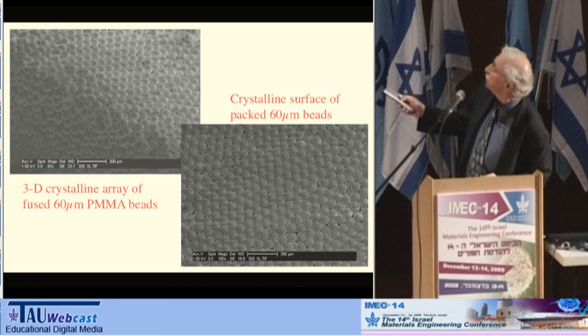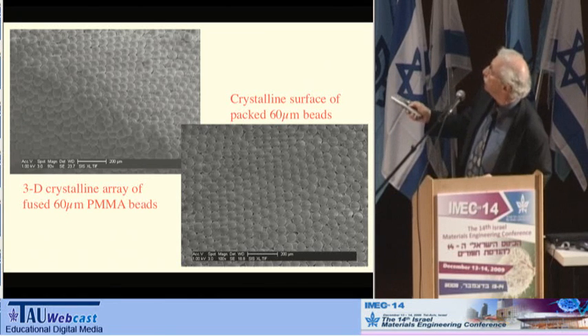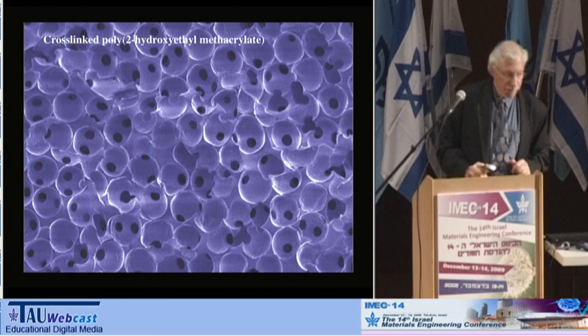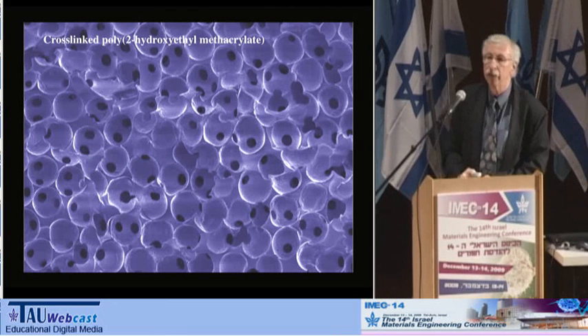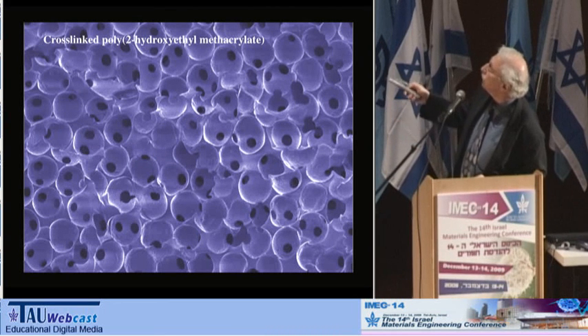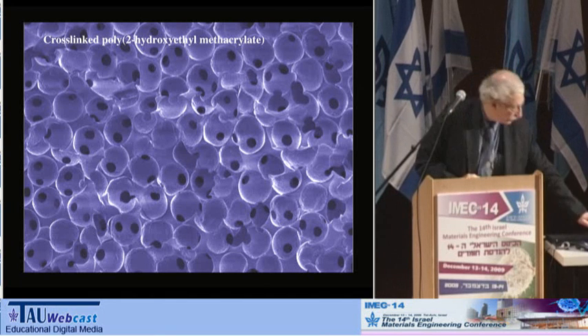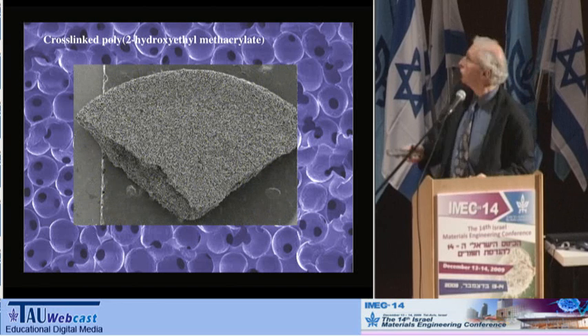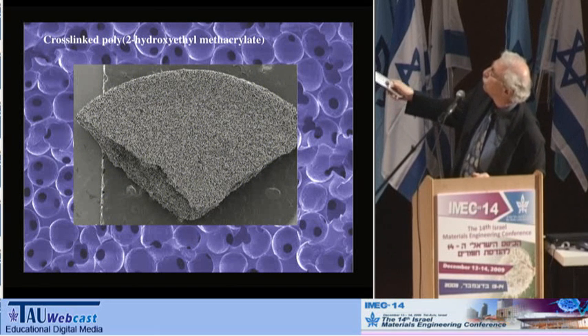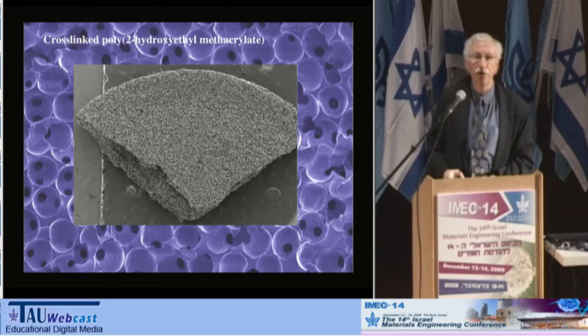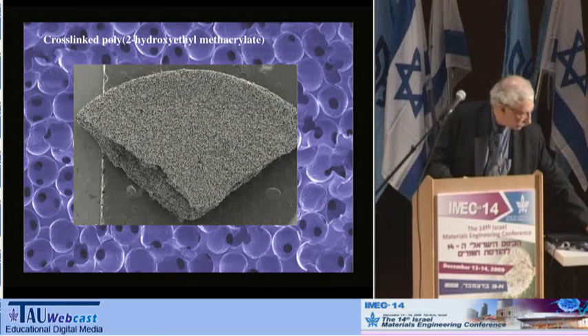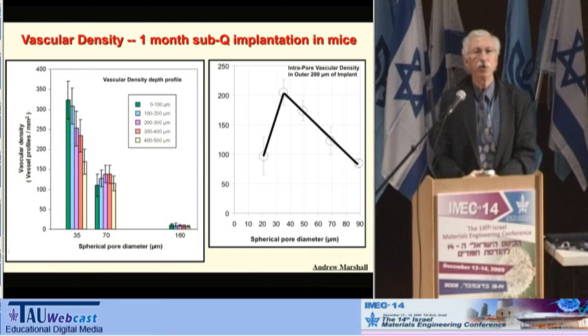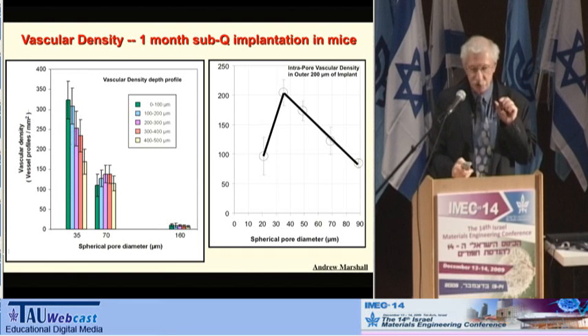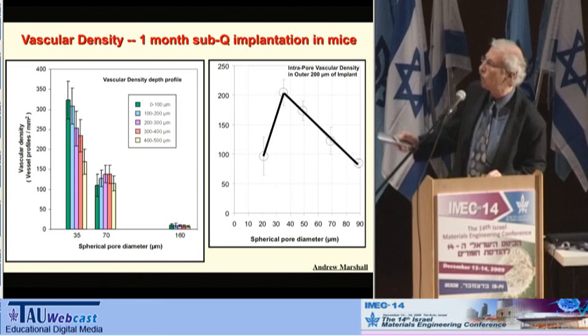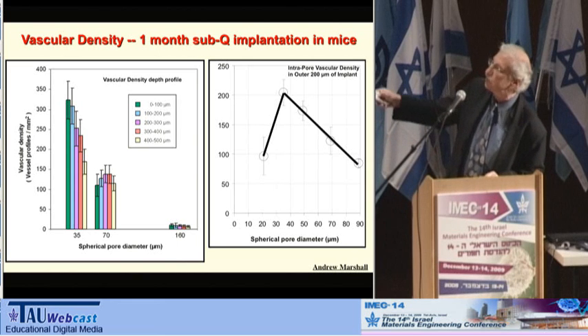So this is what the spheres look like when they're shook down and sintered, and this is what the material looks like. This is a cut through a material, and these black dots are the places where the spheres were sintered together. And this shows a large piece of it, so you can see the uniformity of this pore structure across a big chunk of it, the type we might use in an implant. And the results were very striking. If the pore size was just right, and just right turns out to be around 35 microns, this is blood vessel density.